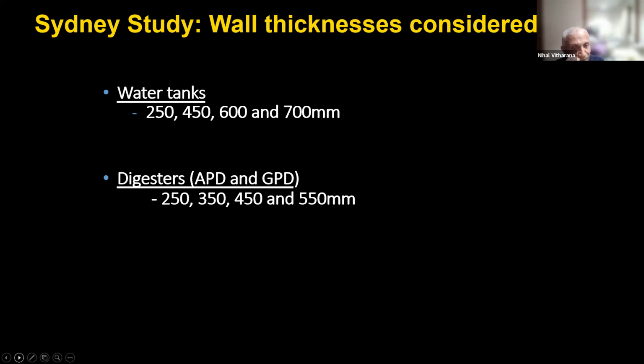So they had a large portfolio of water tanks and digesters, and some information during the operation of these is available with respect to temperature. So water tanks, we consider thickness at 250, 450, 600, 700, and digesters, very similar, but slight change in the thickness. When I said APD, I'm not a process engineer. They are called acid phase digesters. GPD is gas phase digester.